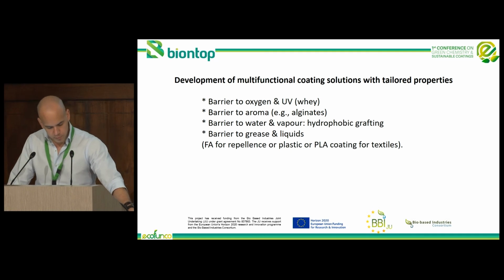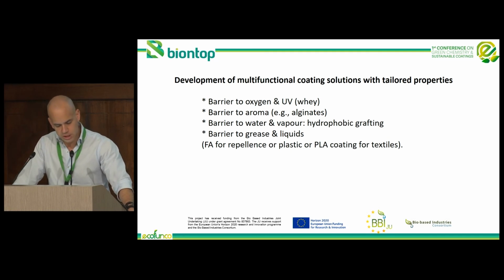In terms of barrier properties, our coating provides barrier to oxygen and UV, also barrier to aroma, thanks to polysaccharides like alginates, barrier to water vapor, to grease, and to liquids. For example, fatty acids for repellents, or PLA coatings for textiles. These multifunctional coatings have a bio-based content above 95%, and are enhancing PLA's oxygen and humidity barrier by a factor greater than 10.